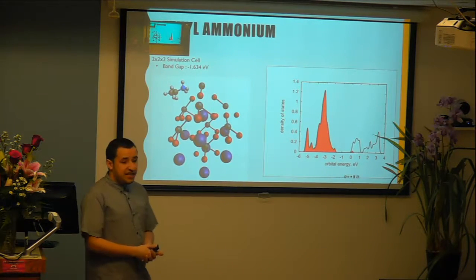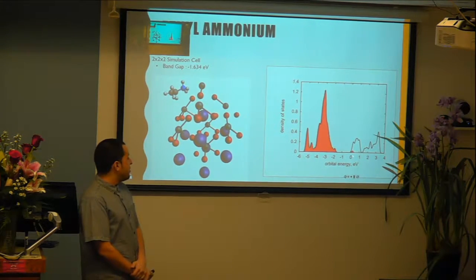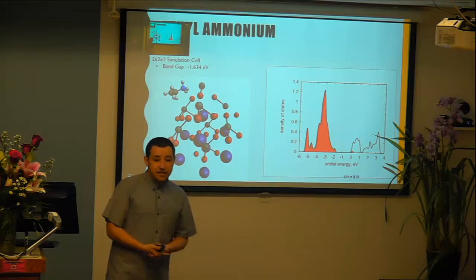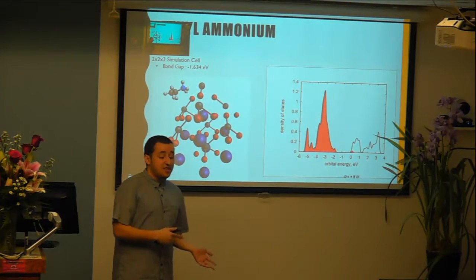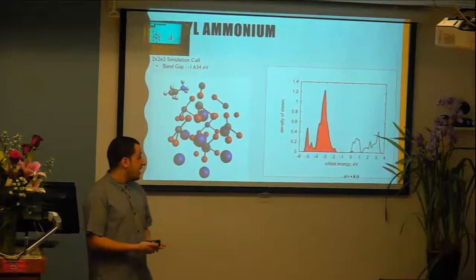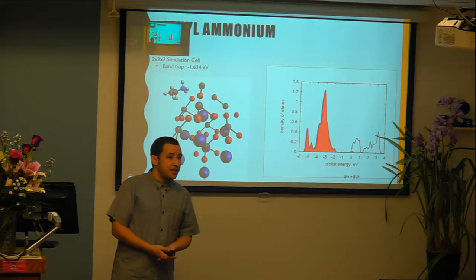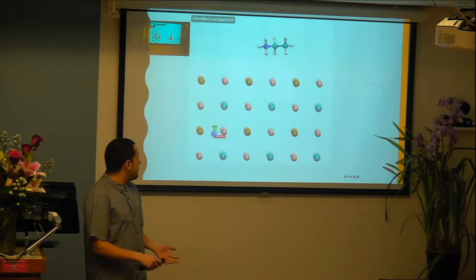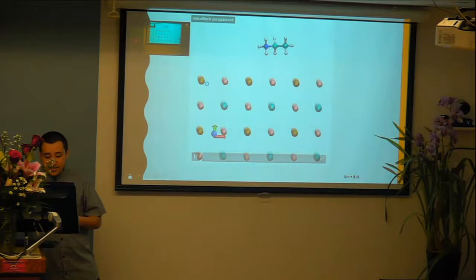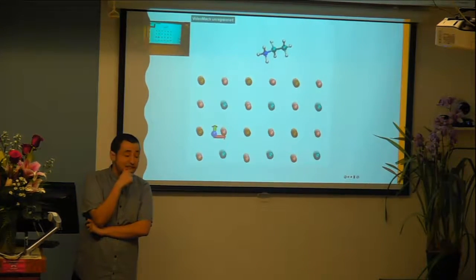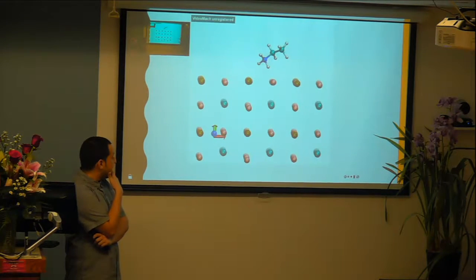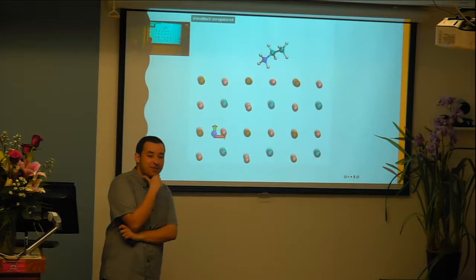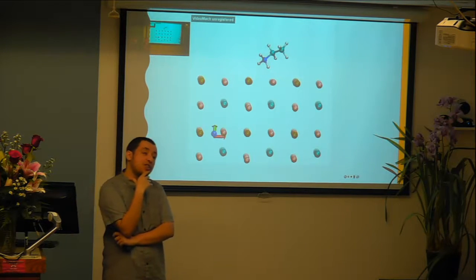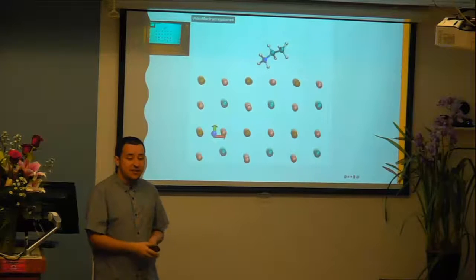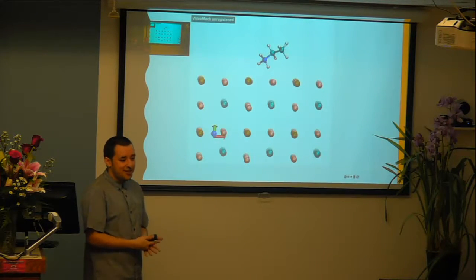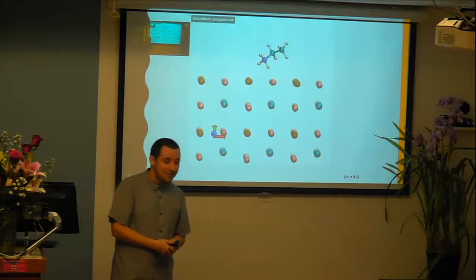And the other ligand I looked at was ethyl ammonium. In this case, you see some density past the conduction band, and basically vice versa to the other one, this makes it a great N-type semiconductor, which makes it a great electron carrier. So whenever we put those together, well, I apologize, I have a simulation of the ethyl ammonium attaching itself to the surface of the perovskite, and that's what it looked like. I was hoping to be more ambitious and have a simulation for all three ligands. The third ligand I'll be talking about in a little bit. It's just that jobs are still queued up in NERSC. Everybody in class knows how tricky it is to get your jobs to run, but that's beside the point.